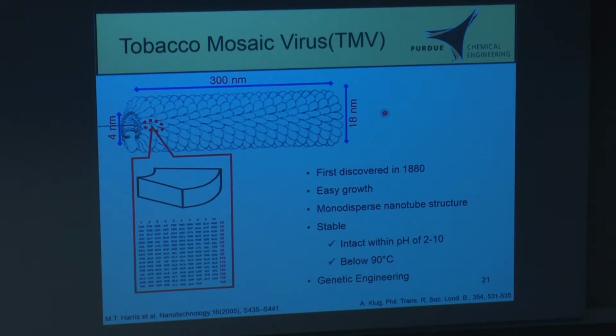The virus is also stable because it stays intact in a pH range from 2 to 10, and temperatures up to 90 degrees Celsius. So that means that you can carry out a number of different chemistries using TMV. And with genetic engineering, you can make TMV be stable even in some organic matrices. We primarily use it in water and in some cases alcohol-water systems, but primarily in aqueous solutions.